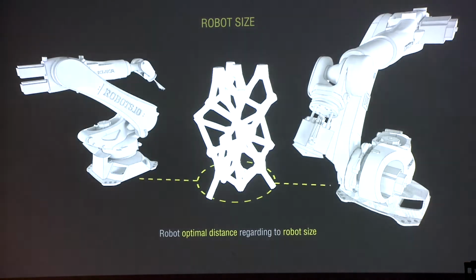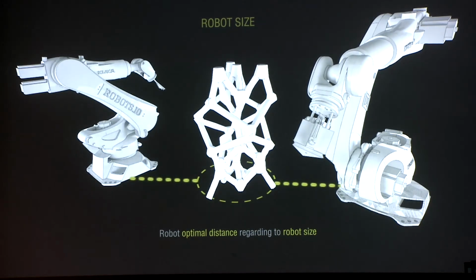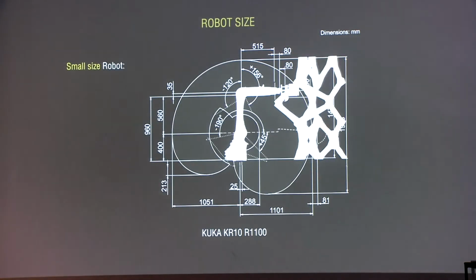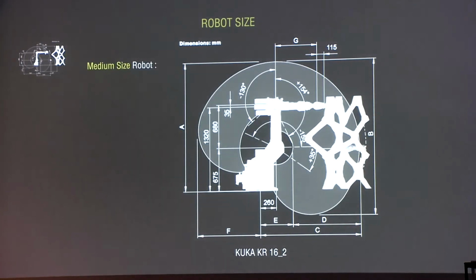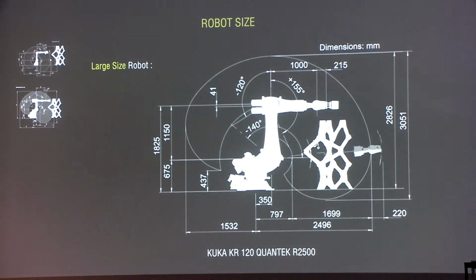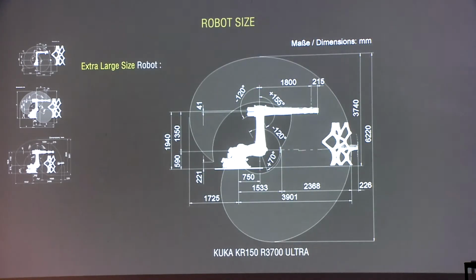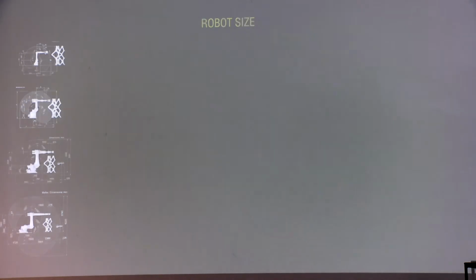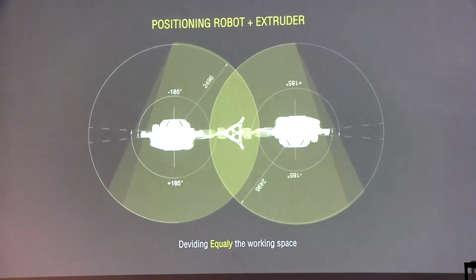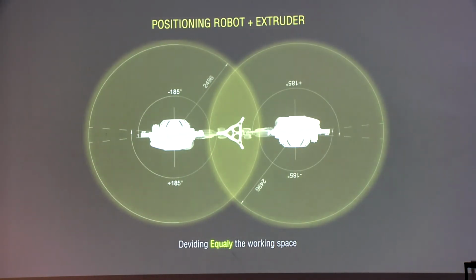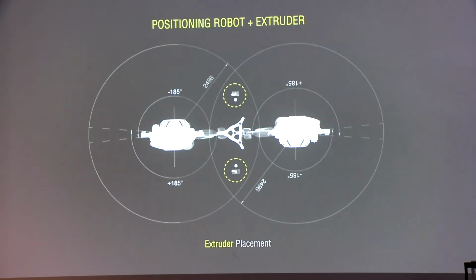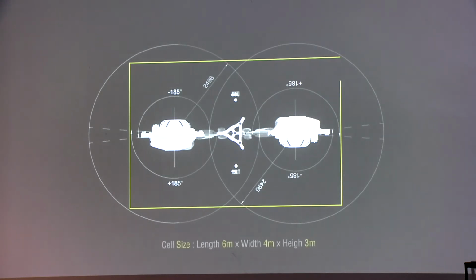The robot size is important to define the distance between the working area and the robot, and we tried to figure this out with different models and sizes of the robot to see which one is needed for our fabrication. The large-scale model seems to be the best one in order to achieve our movement. And as we have two robots, the extruder placement needs to be equally divided in space, so the robot can reach it. We divide the space equally for the two robots as well. That said, the cell that we are trying to achieve seems to be 6 by 4 by 3 meters, and it's the optimal configuration that we need to fabricate our units.